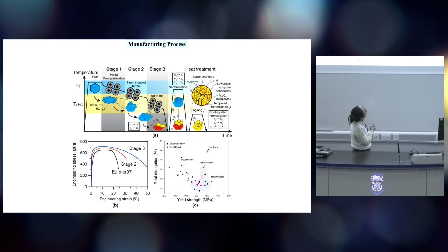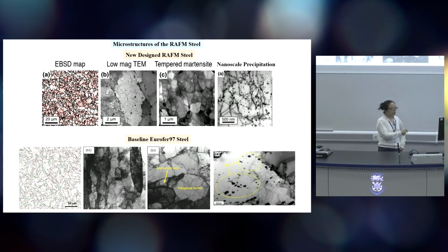This is our work. We combined the ductility and the strength. The ductility increase did not lose the strengthening. Importantly, the stage 3 steel also obtained better total elongation properties compared to the standard Eurofer 97 RAFM steels. And we analyzed the microstructure to give a mechanism explanation of why we can achieve both excellent ductility and strength.